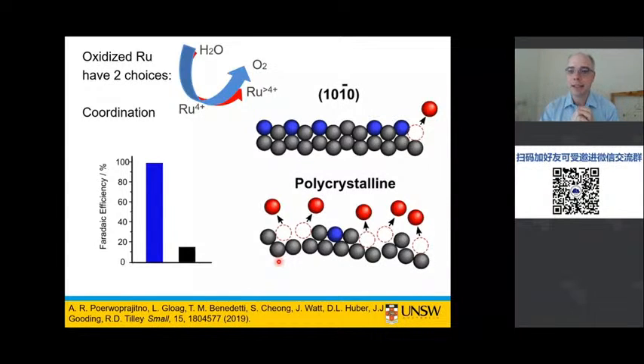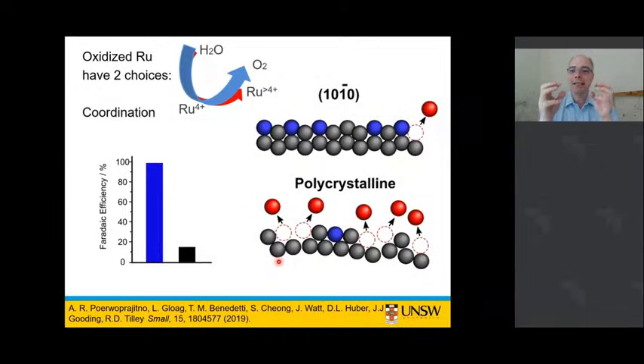If we have these low index facets, we have our ruthenium atoms on these low index facets. They have a high coordination number. So when they're oxidized, they're being held on that facet by maybe 6 or 7 or 8 other ruthenium atoms that are bound to it, holding on to it and keeping it attached to the surface. Whereas if we have polycrystalline ruthenium, when they're oxidized, they may be bonded only to 2 or 3 or 4 other ruthenium atoms, and then it's very, very easy for them to just dissolve and go up into the electrolyte. So this is really an indication of why these low index facets might be what we're after in terms of the catalytic surfaces that we want to achieve.